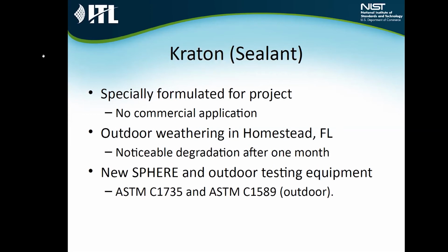The second iteration that I was part of was another sealant named Kraton. Again, not a commercially available material, but specifically formulated for the project. In this iteration, we made a tweak to the tactics, not the strategy. We were still focusing on the same strategy, which is the strategy I put up a few slides back, but we changed the tactic. Instead of weathering the samples at the NIST campus in Gaithersburg, we started weathering them in Florida, which has a much hotter and more humid climate than Maryland. There was more progress made on test methods and equipment, and on this iteration, we were able to completely carry through the strategy, comparing predictions of what we were going to see outdoors to what we actually saw outdoors. And I'll talk about those results in the next 2 slides.